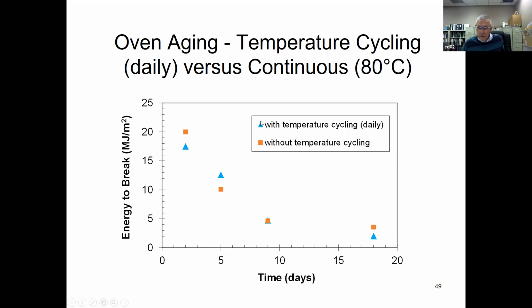Okay, so this is just a one-off experiment. We said to ourselves, if at low temperature you're forming sulfoxide and peroxide, and at high temperature you're forming carbon-carbon crosslinks, we decided to do what we call temperature cycling. So this says a 9-day age at 80 degrees C. There's a sample without temperature cycling and with temperature cycling. Without temperature cycling means it was in the oven at 80 degrees C for 9 days.